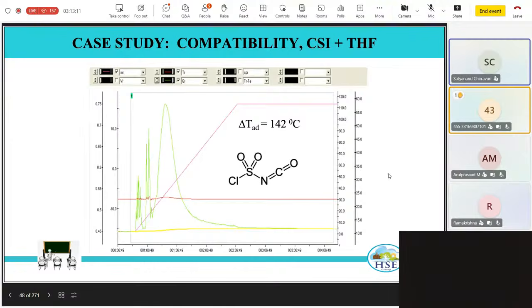And once the reaction was brought to room temperature, what happened was that there was an exotherm. And it was found that once it reaches 30 degrees centigrade, there is no stopping the reaction. The mass itself will go to 142 degrees centigrade.